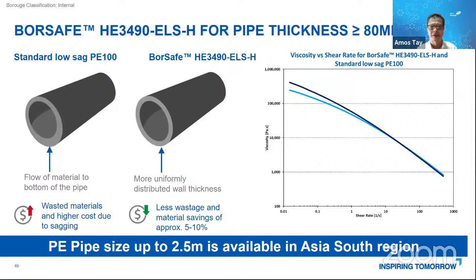So with this new material, designed actually for wall thickness more than 80 mm, because normally if you have a standard PE100 low sag material, which is on the left, you can see that the material builds up at the bottom, because when material extrudes from the machine, because material is still molten, it flows downward. When it flows downward, it accumulates at the bottom, like maybe 4 to 7 o'clock area. So this increases the thickness at the bottom, and you have to do a lot of adjustment and some scraps in order to get a reasonable distribution of this wall thickness. And this could cause a wastage of material, manpower, and also energy in terms of producing the pipe.